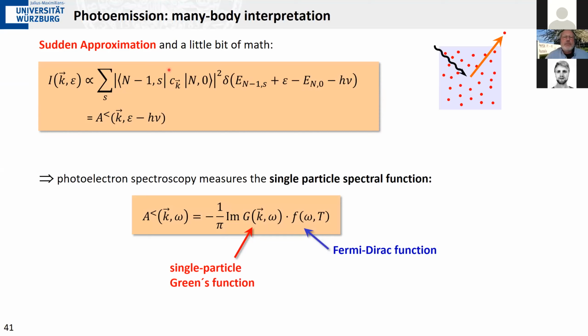And this expression that comes out should be familiar to the many-body theorists among you. This is nothing else but the single particle spectral function, which is basically the imaginary part of the single particle Green's function multiplied with the Fermi-Dirac function, because you can, of course, only excite electrons that have been in the system before. And that's the very strength of this expression or of this picture. What we measure here in the many-body picture of photoemission is a response function that is one of the core properties in many-body theory. And so that gives you a lot of information that you can directly compare to theory calculations.